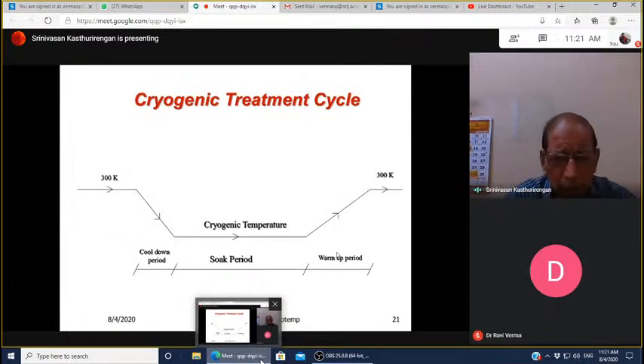So the cryogenic treatment is something like this. You start the material at room temperature, 300 K, and then gradually allow it to cool down to low temperature. Then this is the soak period, where you maintain that cryogenic temperature, then allow it to warm up back to the room temperature.